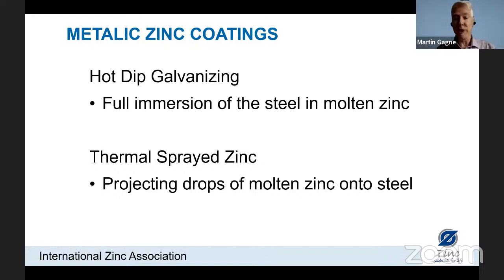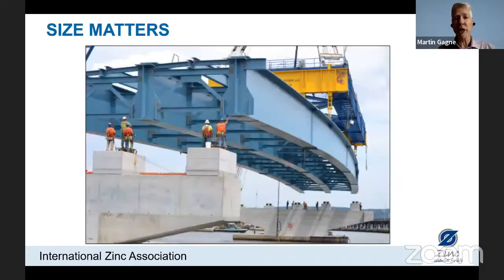Now with thermal spray zinc, it's more like spray painting with the liquid metal. We have a heat source to melt the zinc, and we use compressed air to project those drops of molten zinc onto the steel and build up the coating. So in this way, size is not an issue. We can do this process in the factory or in the field, while hot dip galvanizing is restricted to a factory application because the size is important.